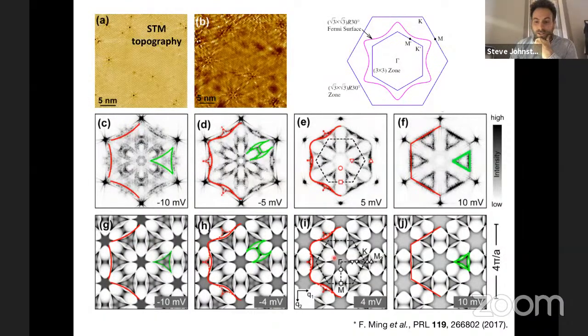Down here, these are calculations that are done in this T-matrix formalism using, again, this non-interacting band structure, and no other parameters have been adjusted other than the strength of the impurity potential. And here again, we see features that sort of look like what's going on in the experiment here. There's, again, this nice Fermi surface, 2KF type image, and then we get these triangular-like patterns forming from this Umklapp scattering. And they disperse in a manner very similar to what's happening in the experiment. They don't flatten out as much, and we think that has to do with some many-body effects that we haven't included in the problem, but we do see some dispersion.